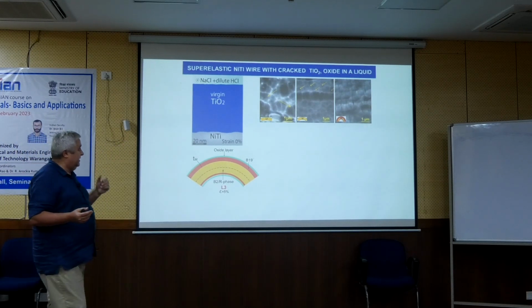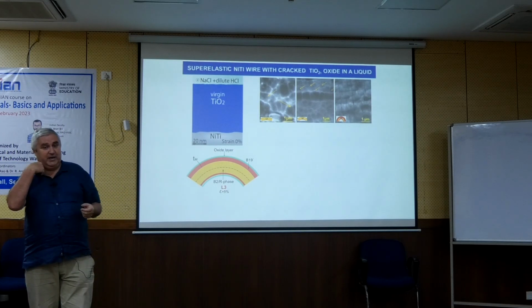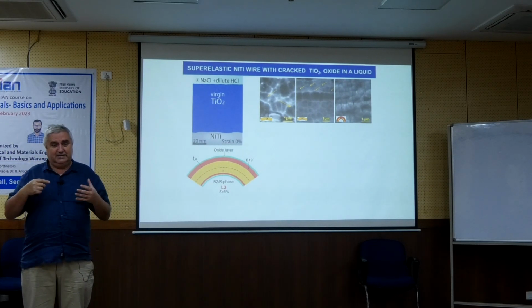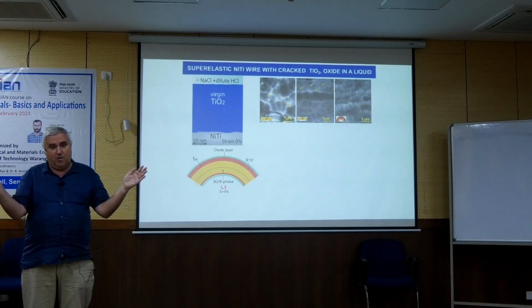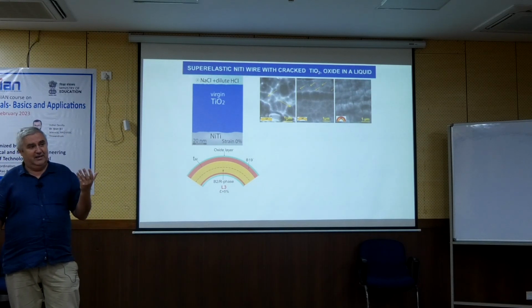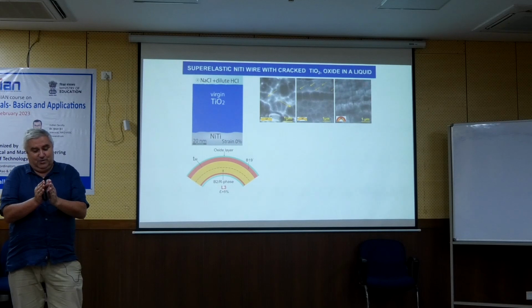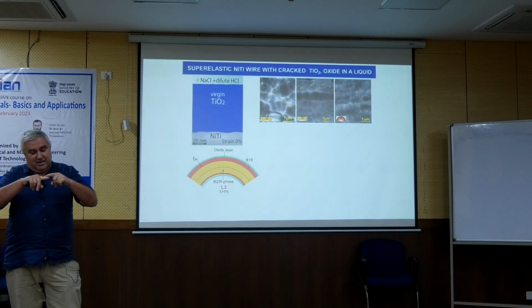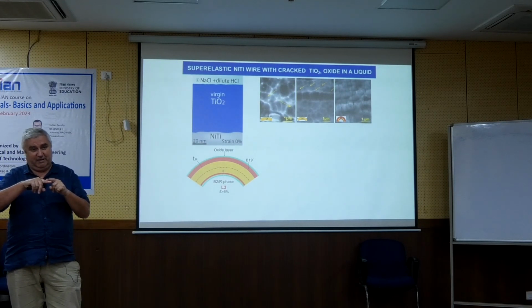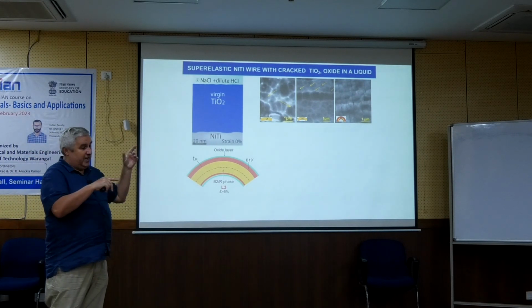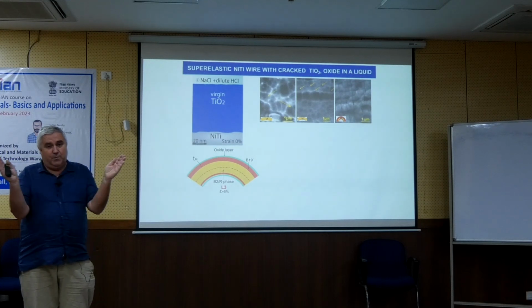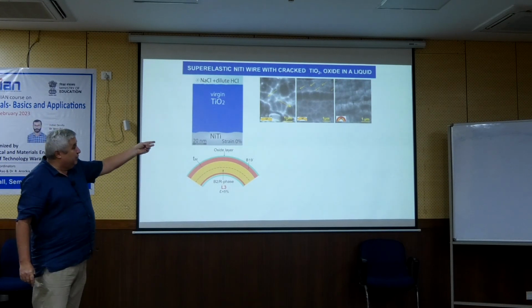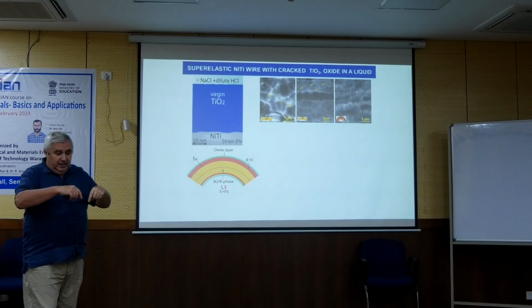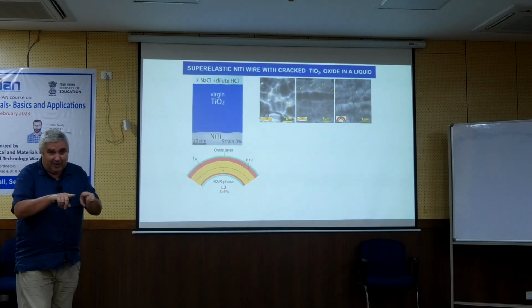But when you have the stent, this esophageal stent, when you are eating and the stent is working actively, these cracks are opening, closing, opening, closing. It means that every time the wire is stretched, and because the nitinol wire deforms 5%, you have surface strain 5%, and this ceramic oxide cannot survive 5%. So what happens is that these cracks which appear in the first cycle, upon further cycling they are opening, closing. We could see it. If we put the sample in the SEM and look at it, we have seen how the cracks are opening, closing.